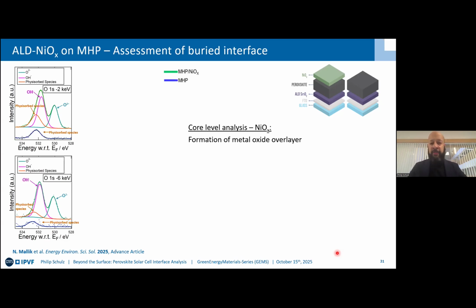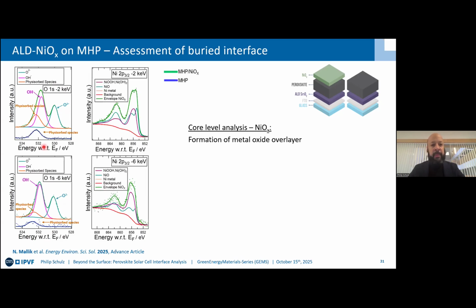The situation is different for the nickel oxide. So yes, you get your metal oxide overlayer, but if you make the comparison here of the oxygen 1s core level from 2 keV to 6 keV, you can already see that it's not just the O2- moiety that you get, and that belongs to phase pure NiO, but you also see hydroxide groups arising, and of course some physisorbed species that come out more clearly at 2 keV.